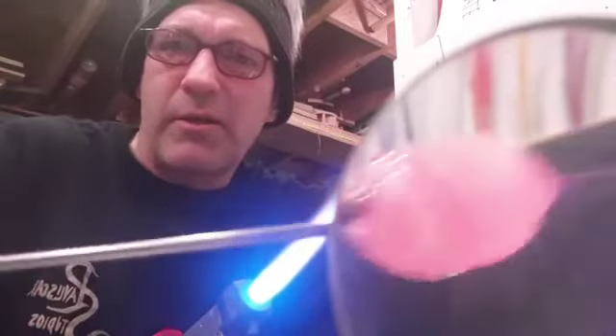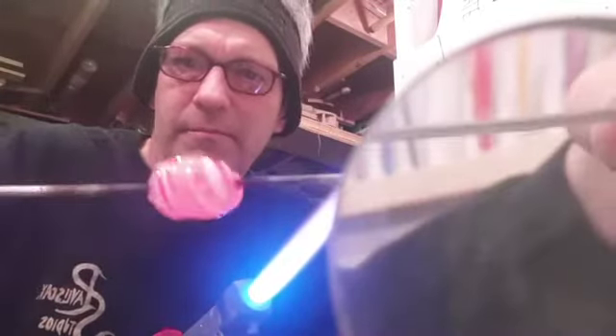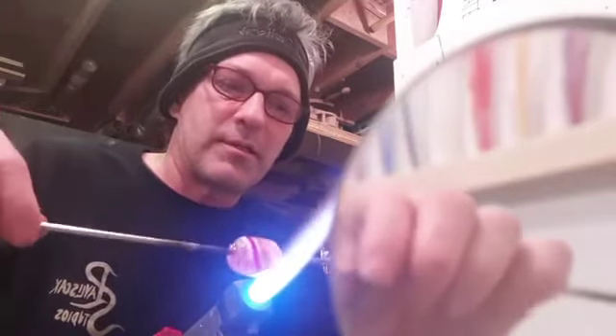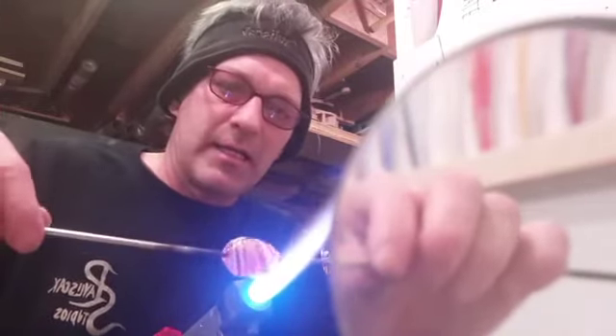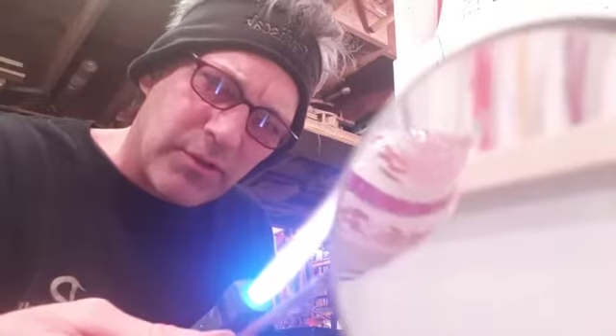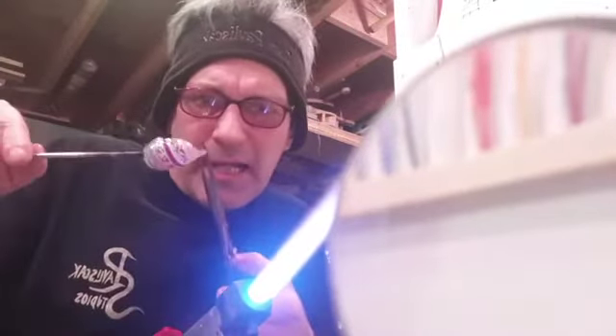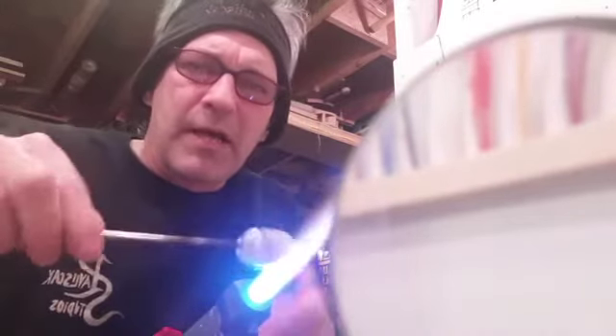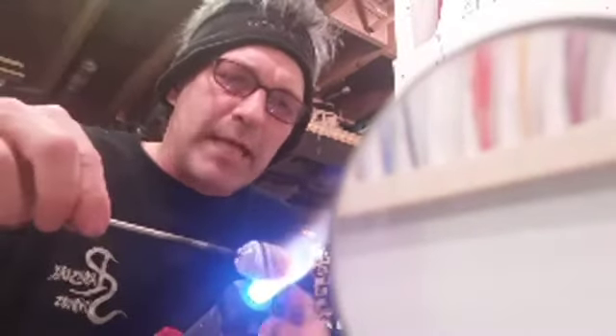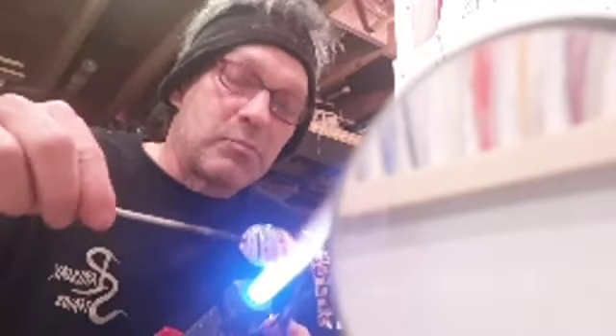All right, so I put my twist in already. Looks good. Now I'm going to detach this handle that I just put on to add the twist. And I'm going to clean up that end and get all the lines and the spirals and the enamel colors. Right now, they don't all come to the end. You can see they sort of spiral out. What I want to do is come back a little bit farther in, and I'm going to define a cut line, a jack line on this, and then pinch it down, or jack it down, until it's small, and then I'll tap it off.